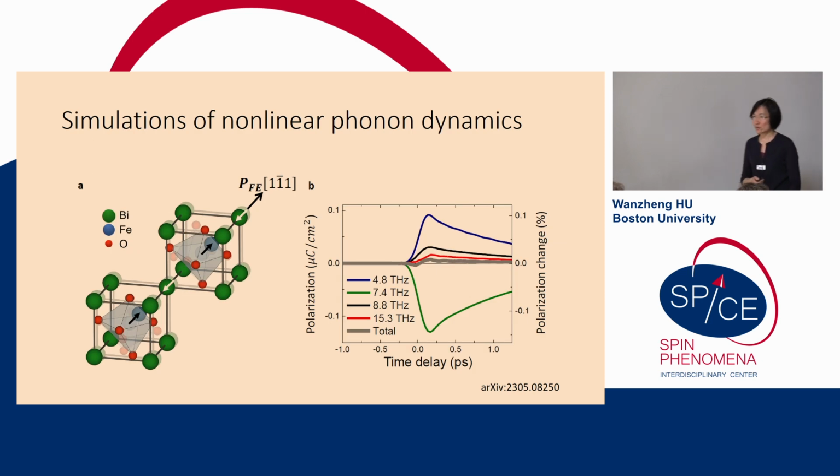And to understand what exactly happened to the structure, we collaborate with Dominik Juraschek and Michael Fechner. They did a first principle calculation, and in the phonon-driven state, they considered the coupling of the high energy A1 mode we drive to all the low energy modes. And then they predict how each atom is going to distort in the pump-induced state. And very interestingly, if you remember, I said in lithium niobate, the polarization contributions of the lithium and niobium are aligned along the same direction.